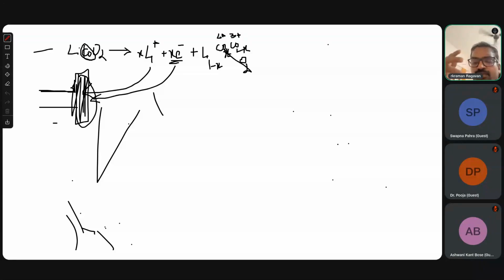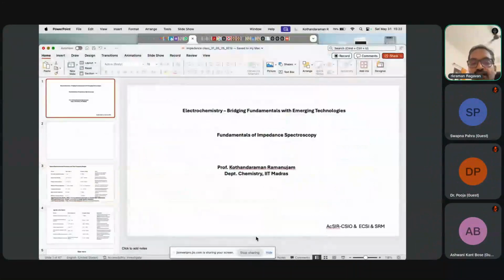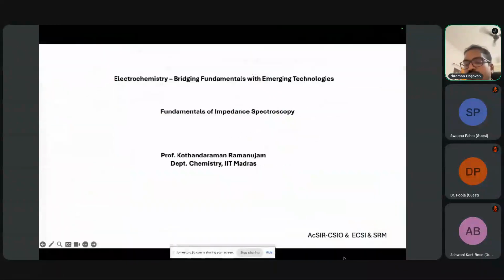So if you see, it is a lot of processes here. One is there is a redox process at the anode, there is a redox process at the cathode, and there is a transport of the species in the solution, and then the species has to diffuse through the SEI layer that is present. Okay, so there are many events which happen simultaneously during the charging and discharging of this battery. Now each of those events can be understood using impedance spectroscopy. They possess something called a time constant. Because each of those events possesses a different time constant, we can distinguish them in impedance spectroscopy.